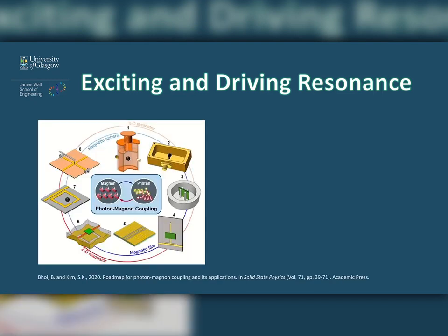In the cavity magnonics community, there are a few currently favored ways of doing this. At the top here we have some 3D cavity resonators, within which we have an example of YIG spheres. YIG is one of the most favored materials at the moment because it's very low damping, which gives the magnons a longer lifetime. Antiferromagnetic materials such as hematite are also being studied, and I've been looking at permalloy in these setups.